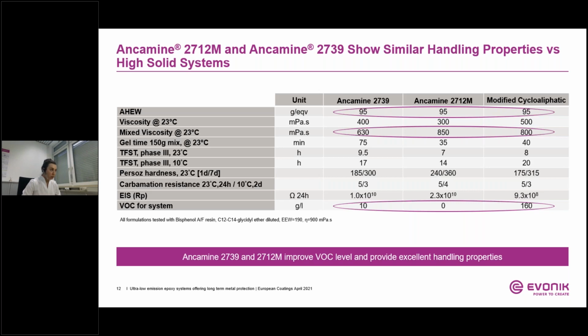The barrier properties of the clear coats have been investigated here as well by using electrochemical impedance spectroscopy, where in all cases pore resistance was above 10 to the 8 ohms, which indicates excellent corrosion resistance.